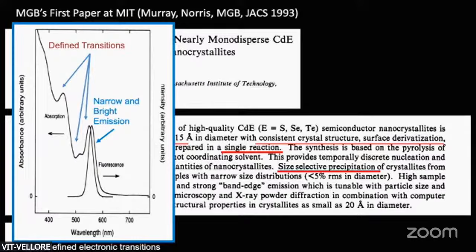And for the first time, for these materials, we actually saw emission that was, I thought it was bright, and the color was quite narrow compared to other materials, and we call that saturated. The color was saturated. And I was so excited that I thought it was so bright. The quantum efficiency was 20%, which means that only 20% of the photons, the blue photons, resulted, after being absorbed, in a photon of a different color coming out.